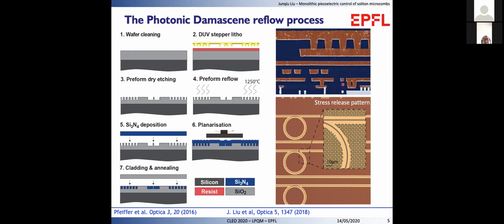This process was inspired by the copper dual Damascene process used for copper interconnect circuits. An advantage of this process is that we can pattern the crack barrier pattern to release the high tensile stress of silicon nitride to prevent crack formation.